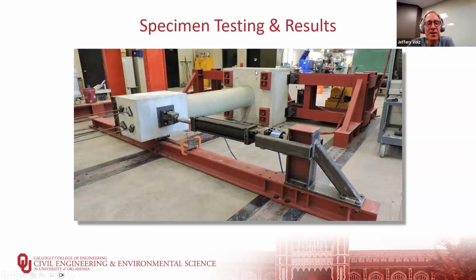So here you see the base anchored to the frame through 8 high-strength threaded rods. They go through the concrete, through those PVC tubes that were in the formwork that you saw, and they penetrate through the W24x68 flanges and then are anchored on the backside. This is our hydraulic ram. It has about a 26-inch stroke, so it is showing extended halfway because we push on the column in one direction, pull it back to 0, and then pull it back the same distance in the other direction.